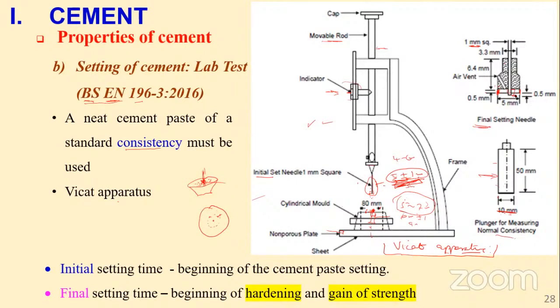So for the final setting time, now this can't penetrate. If we release this here and it penetrates, and even the edges here dig a circular mark, too much that is visible, we know final setting has not occurred. But if it's able to penetrate just 0.5 and then just make a mark using these edges of a hollowed out metallic attachment, then we say final setting time has occurred, right?